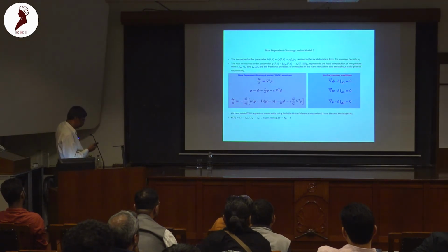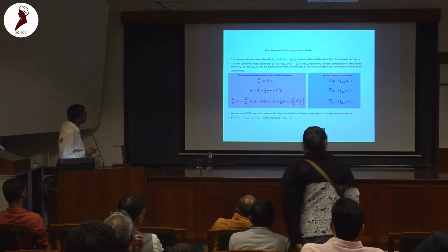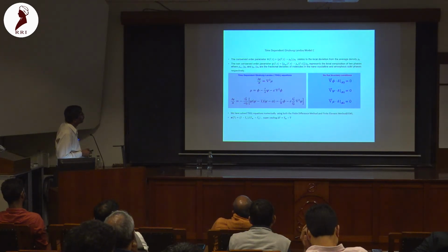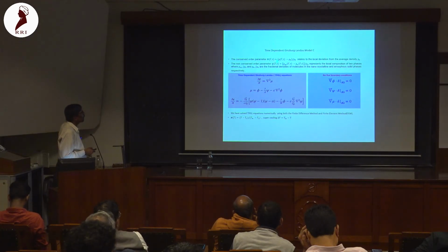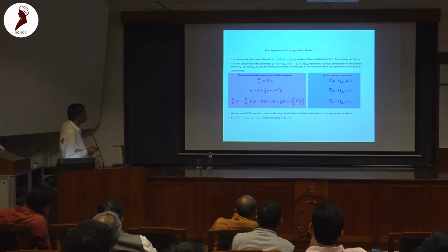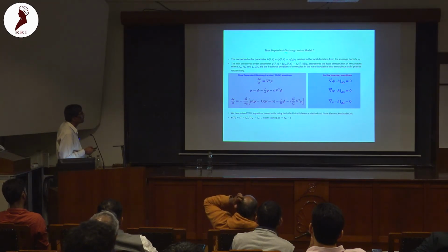Okay, so then to understand this, there is a model called the time-dependent Ginzburg-Landau model. So we define two order parameters. One is the density variation, and one is the order parameter to take into account the phase transition to the crystalline state. This being a density, it is a conserved order parameter. That means that this quantity integrated over the whole volume will remain constant, and the other is a non-conserved order parameter. For these two order parameters, there are some well-known theories for their time-dependent equations.